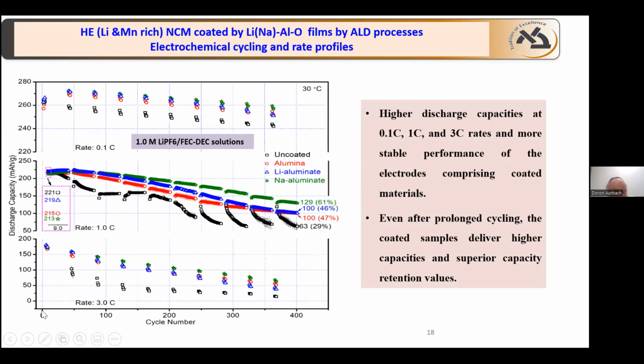It can be pouch cells or coin cells. During hundreds of cycles, here the electrode can be lithium or graphite, and we compare coated material with different alumina, lithium aluminate, sodium aluminate, and we see big differences. So what we do, a few cycles at a low rate, so we have the very high capacity, which is nearly 270 milliampere hour per gram, which is very high, and the reference is lower.